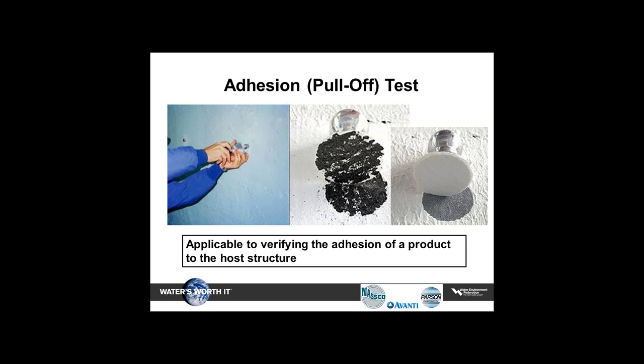Adhesion pull-off tests. Pull-off tests are typically done to verify that the product has properly adhered to the structure surface. And this is where the preparation and the pre-cleaning and pre-testing becomes very, very important. And you can see on the two slides, the darker one is where this dolly that is glued to the coating has been pulled off, and we can see substrate material, not just the coating, but substrate material, which tells us that the substrate has actually failed during the pull and not the adhesion or the bond of the coating to the substrate. And the second one is obvious, where the coating has pulled right off of the substrate and did not bond very well. So we want to test for those things because we want to make sure that the product has adhered properly. If it has adhered properly, you probably have a long-term solution.